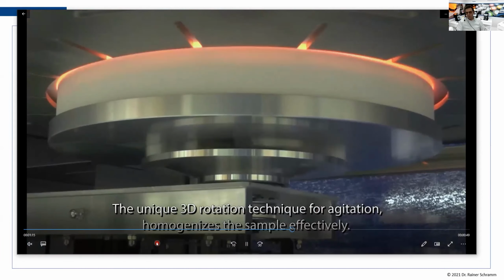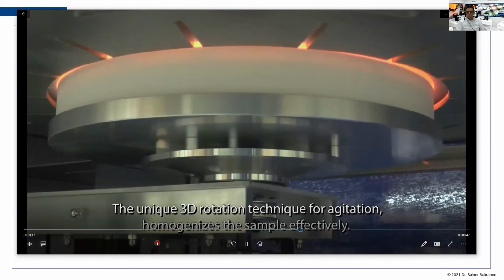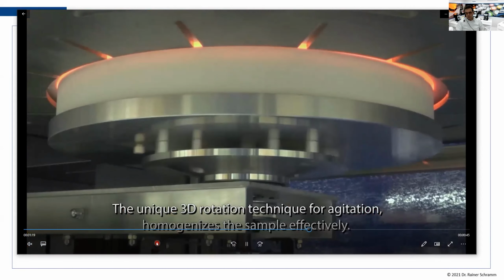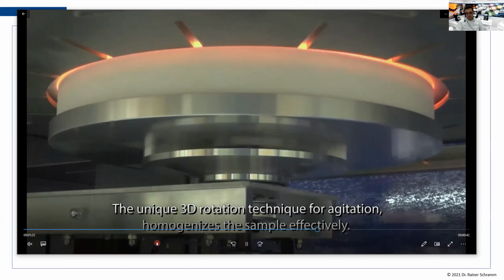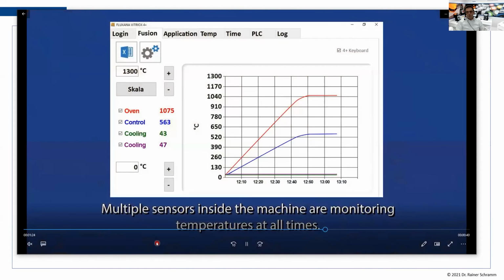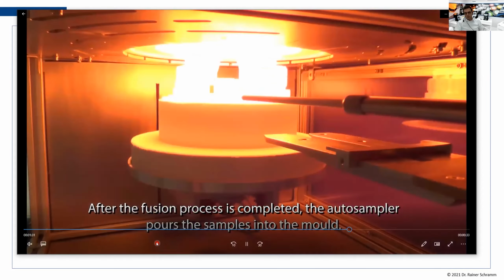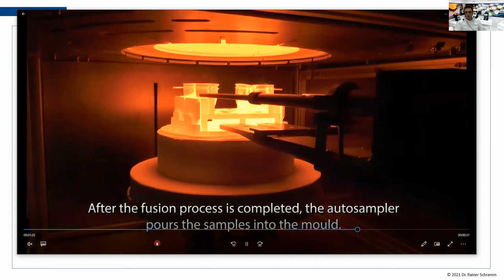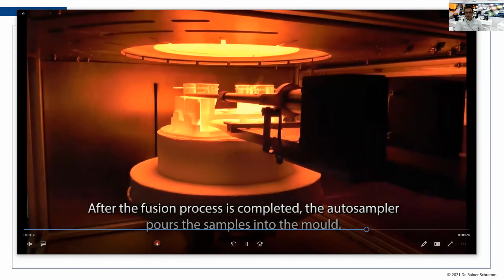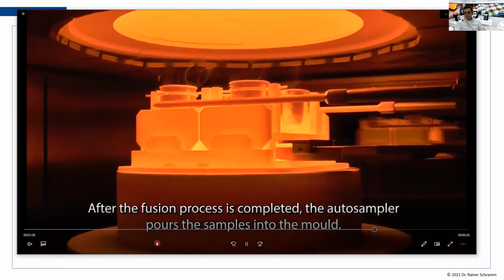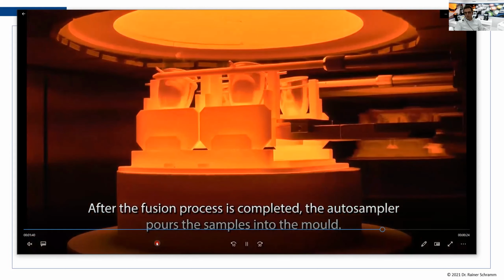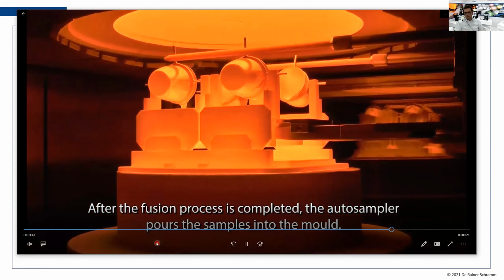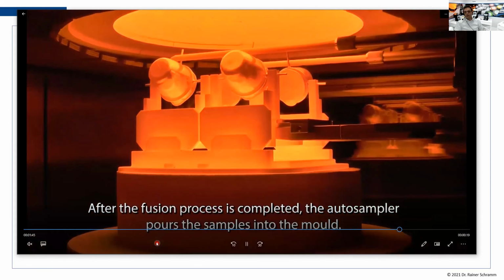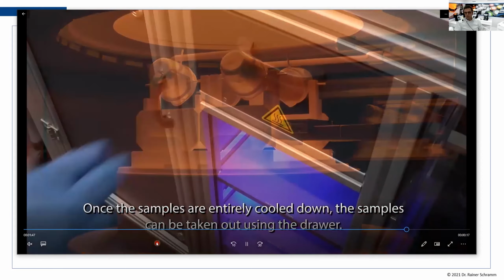And this is the high-speed agitation in both directions, so that you really mix it inside. And because all of our crucibles are sitting on a circle, it's exactly the same stirring for every crucible. So once it's finished, the autosampler comes back, takes the rack, and pours all 4 samples at once into their molds. In this way, we guarantee that every melt sees the same time, same temperature.